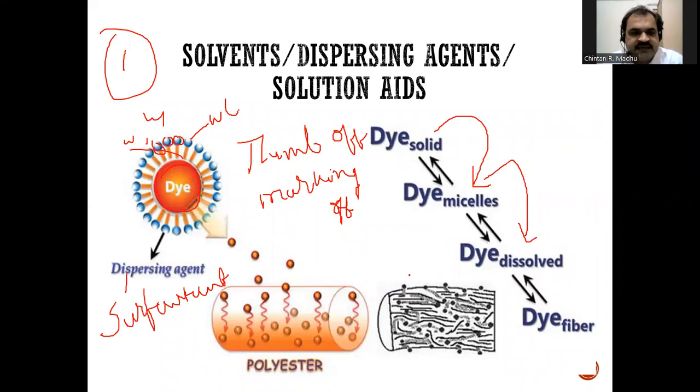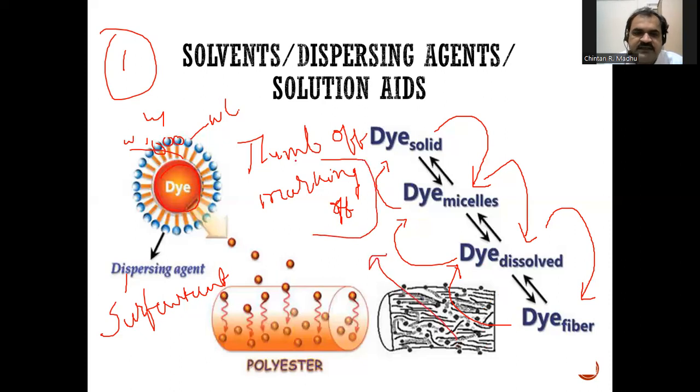That's why it is known as the solid colloidal solution. We will discuss this in our further lectures when we are talking about the printing of polyester with disperse dye. Your dye will penetrate the fabric surface, which means the dye is dissolved in the fiber, and then you will achieve the printing. This will reverse if you do not control your temperature and pressure during the fixation process. When this reverses, you will generate the marking effect, which we do not want.